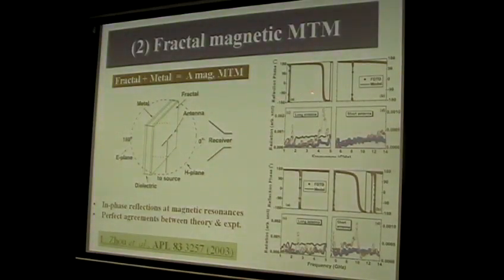And we perform an FDTD simulation to calculate the properties. Because this system is totally reflecting, because it has a perfect PEC layer on the back, only the phase can be relevant. And this is the phase repeated here. And remember that I have shown you that if you have magnetic response, the reflection phase will be in phase. So indeed, you can see that at most frequencies, the reflection is still like metal. However, at some frequencies, the reflection phase changes continuously from pi to minus pi, indicating that a magnetic response appears here.